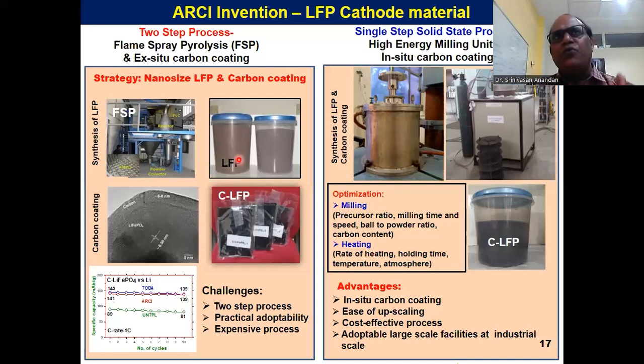As it is a LiFePO4 particle, it is not electrochemically active. You need to have a carbon coating on LiFePO4. We did the carbon coating in the second step, and we were able to do a uniform carbon coating with a thickness of 5 to 6 nanometers. And then finally, we validated the material performance in half cell mode. This is the graph. It shows the capacity of ARCI developed LiFePO4. The x-axis is the number of cycles, and the y-axis is how much current it can deliver per gram of material.